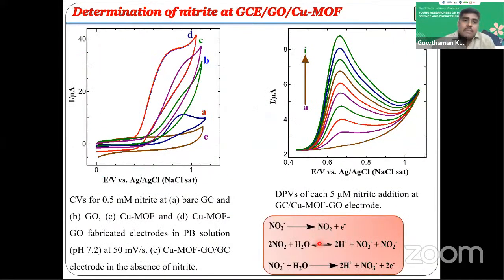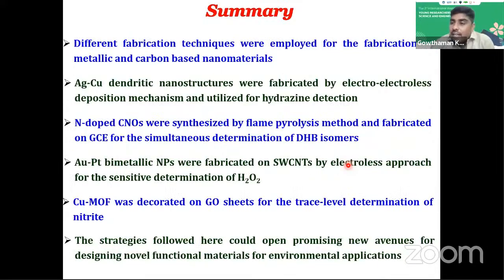This is the interesting point here, and we utilize the modified electrode for the sensing of nitrite in environmental water samples. The graphene oxide copper MOF containing material exhibited higher electrocatalytic activity towards nitrite in the range of 5 micromolar to 50 micromolar addition. So this is my concluding remarks.